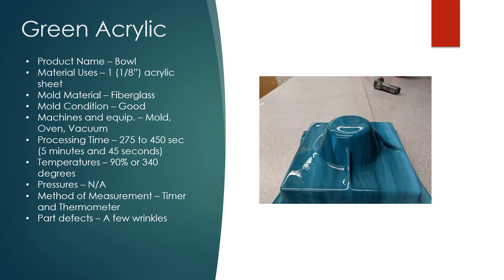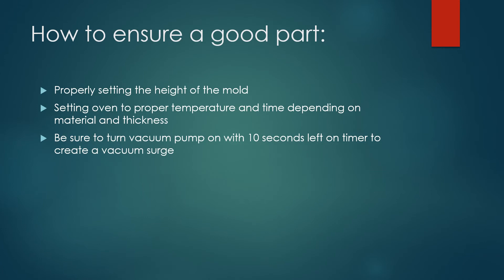It didn't mention anything about pressures again. We used the same methods of measurement, the timer and the thermometer. Similar to the last couple parts, the only real defects on this one: with acrylic, it doesn't really draw the corrugated pattern on the inside as much at all, and there was a few wrinkles.